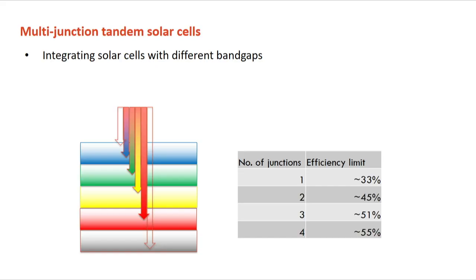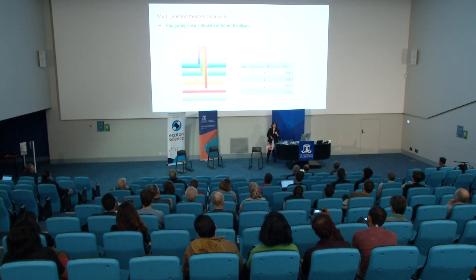So why don't we stack solar cell materials with different band gaps on top of each other? Starting with the very high band gap material that absorbs the UV light really well, and lets the blue and the green and the yellow pass through, and then feeds it to the next stack. The next stack takes the green and yellow and red, and infrared goes to the very bottom of the solar cell. By doing that, you can see the efficiency increase from 33% to 55% for 4-junction cells. As you go higher, the increase is marginal, and therefore there's a trade-off. You don't want to make the solar cell so complex that the additional gain is not worth it.